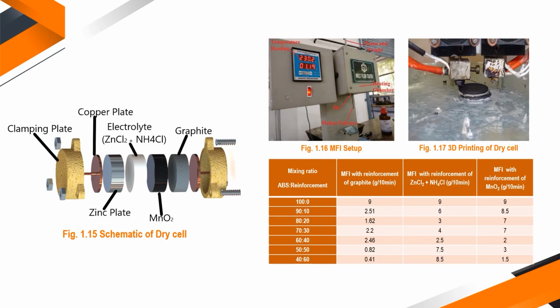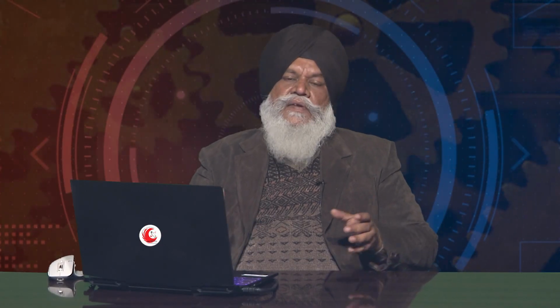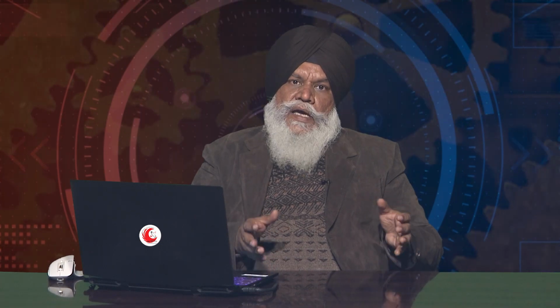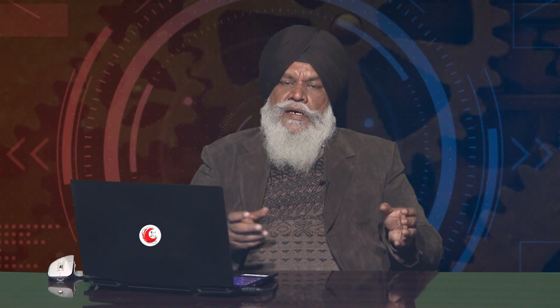So for that purpose, I need to understand the rheology, that is the MFI. As you can see in this table, initially selecting 100% ABS, I am getting an MFI of 9 gram per 10 minutes. Once I add 10%, 20%, 30%, 40% graphite, or zinc chloride, ammonium chloride, or MnO2, I am getting a different value of the MFI. Now what I want for my setup is that this should be in a particular range, and the whole disk should have a near similar composition. Whatever is consumed at the faster rate, I will replace that disk and reassemble it.